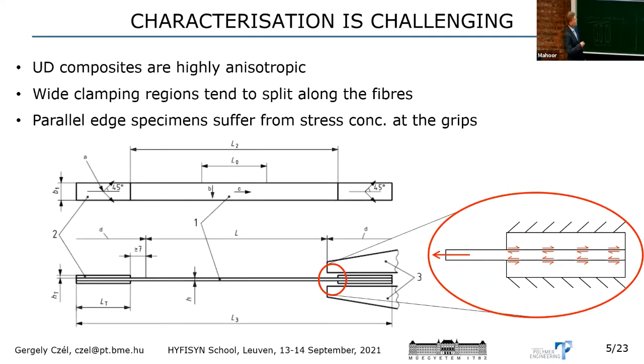And this on its own will result in a combined normal and shear stress state at the tip of the end tabs. So people, and also myself, I thought that the compressive stresses coming from the gripping force are the most detrimental effect to the specimens, but actually not. This combined shear and normal stresses are the more problematic issues. But of course, on top of this, we still have the normal forces from the grip faces. But this usually actually helps when it comes to this debonding, for example, between the end tabs and the specimens. A little bit of normal force, compressive force can even help.